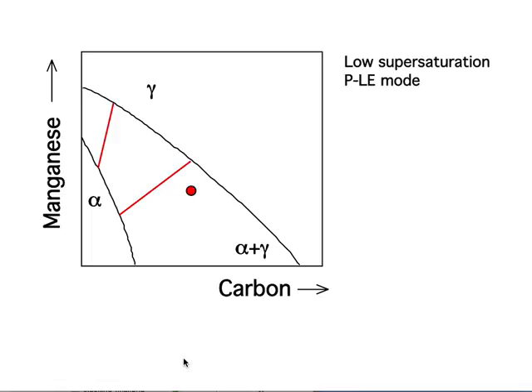Okay, so this is all in your notes, all right? Here you have ferrite, and this is the austenite phase field. So if I go to a high temperature when the alloy is fully austenitic, and then I cool it so that it falls within the alpha gamma phase field, but it's quite near to the austenite phase boundary, then the driving force is going to be small. Okay, so we say there's a low supersaturation. So I've got an alloy here, and I want to pick a tie line which will allow the carbon and manganese fluxes to keep pace even though the diffusion coefficients are very different.